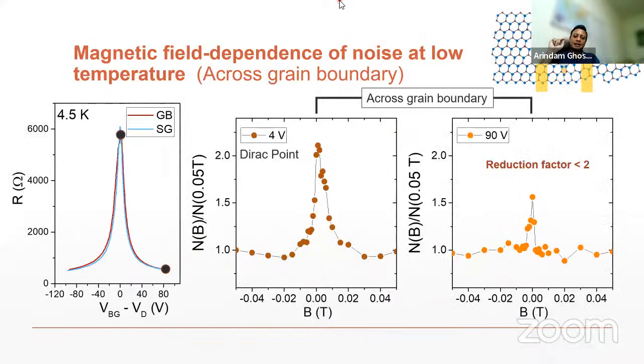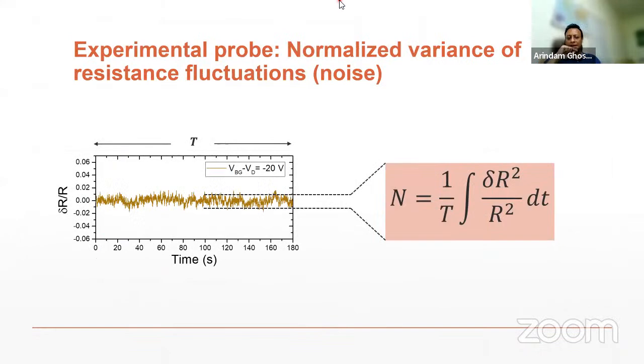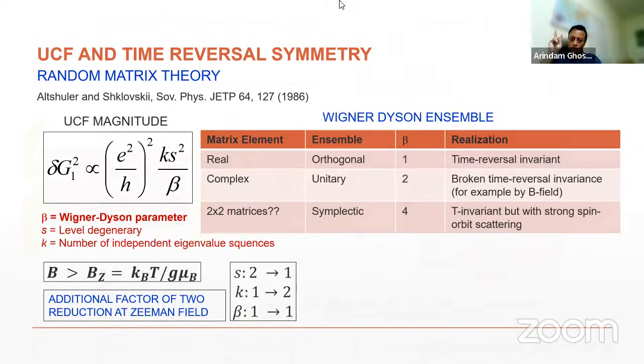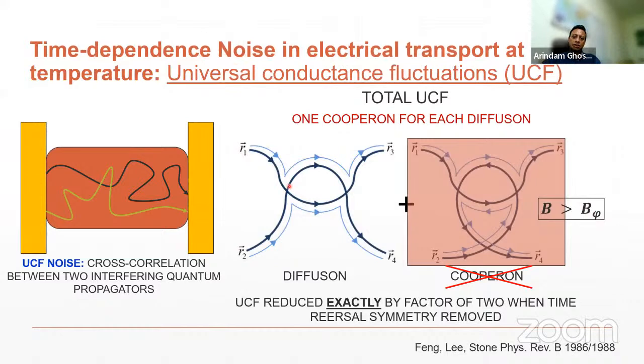So in any kind of disordered system where electrons move in a diffusive manner from one end of the sample to the other, there are two independent contributions to noise. Remember, if you have a disordered system, the electrons are going in diffusive paths, which you can tentatively call Feynman paths as well. So noise is a cross-correlation between these two paths. So I've drawn these two paths here.